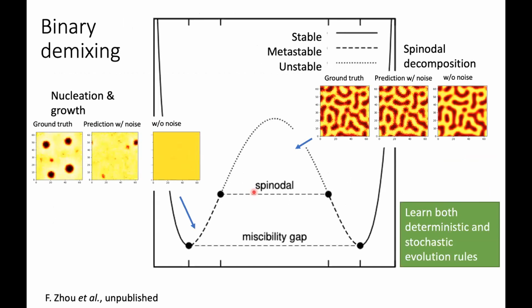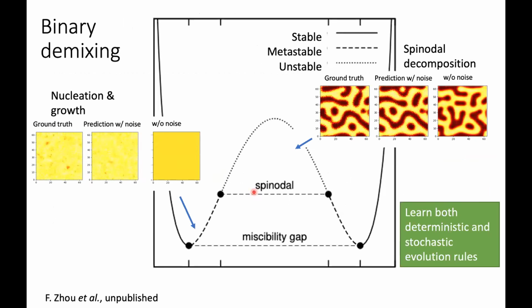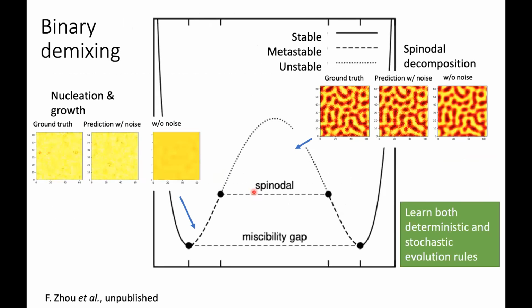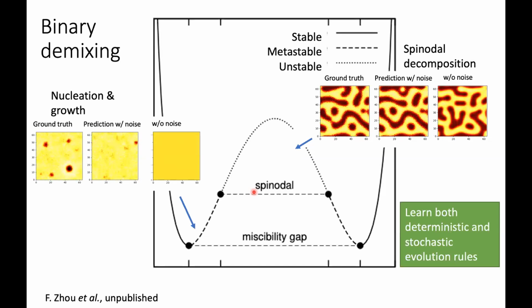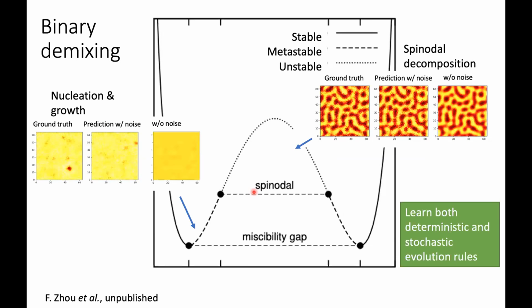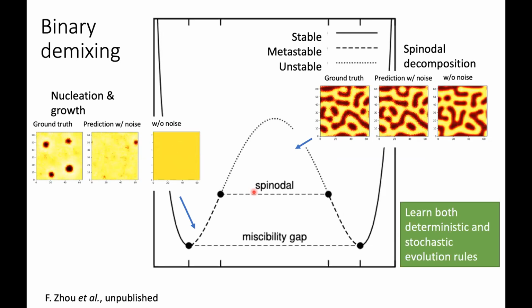And here I'd like to show you one simple example of our work in progress, really a recent development. Here we care about learning not only the deterministic driving force of microstructure evolution, but the stochastic fluctuations. So this example is a binary immiscible system, and the free energy surface, as you can see, is a typical double well. And within the miscibility gap, we have an unstable region and a metastable region.